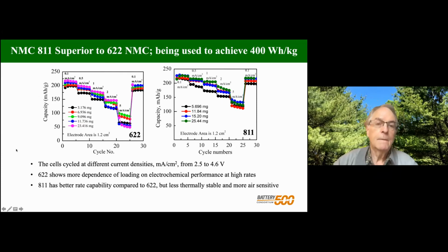So to get higher than 350, we needed to increase the nickel content. So we wanted to see whether 811 was potentially as good as 622. I don't want to go into all the details on this slide, but just look at the drop-off here as you increase the current density, much more than the drop-off with 811. So 811 is a more high-power material. Increasing the loading of the 811 from 5 to 25 milliamps per square centimeter is not as damaging to the rate capability as it is to the 622. So the Battery 500 consortium has switched over to 811. Okay, so this data is actually to 4.6 volts. We know that 4.6 volts gives bad capacity retention, so most of our data on long-term cycling is cut off at 4.3 or 4.4 volts.